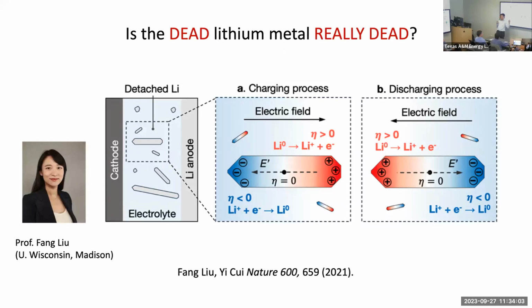This whole thing, the dendrite, will move to the right from the screen, to my right, during charging. During discharge, it's the opposite. This dendrite will move in this direction. Imagine if this dendrite moves a long enough distance, it's going to touch the lithium metal anode and be connected electrically. The dead lithium is alive. It's very interesting. This is a hypothesis.